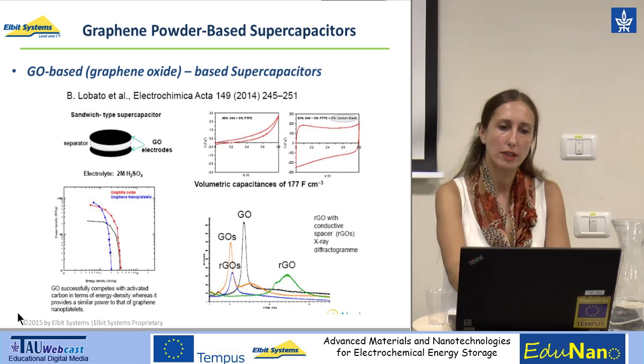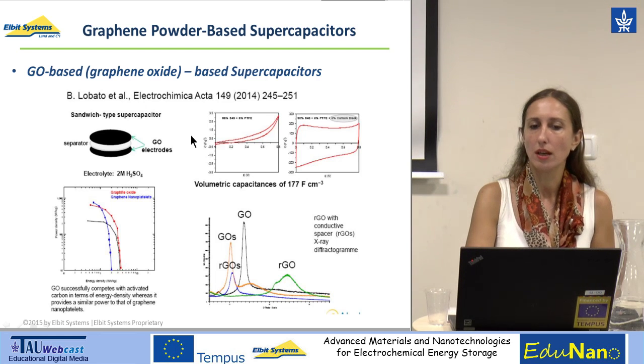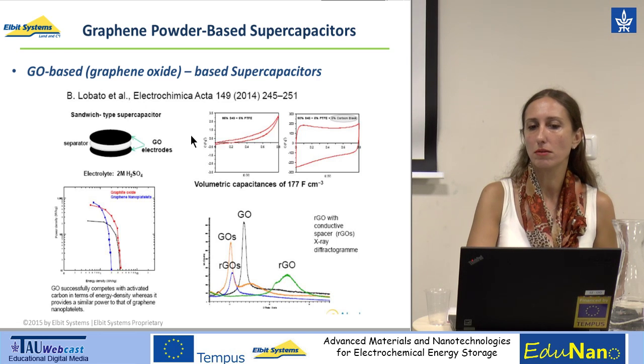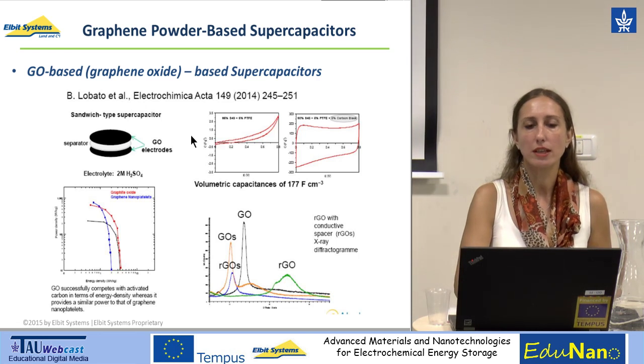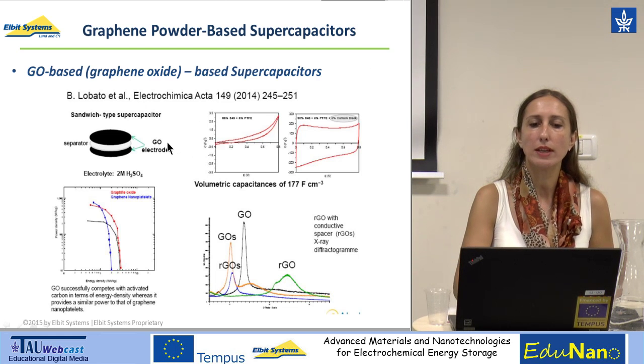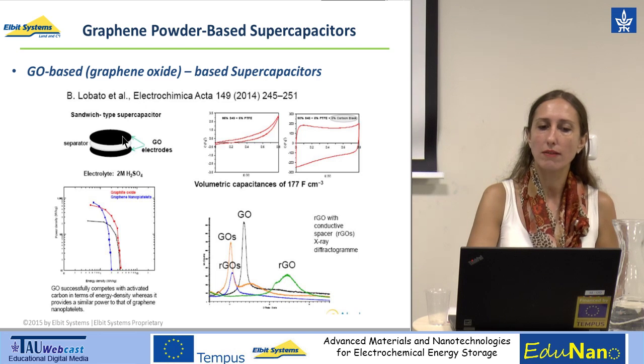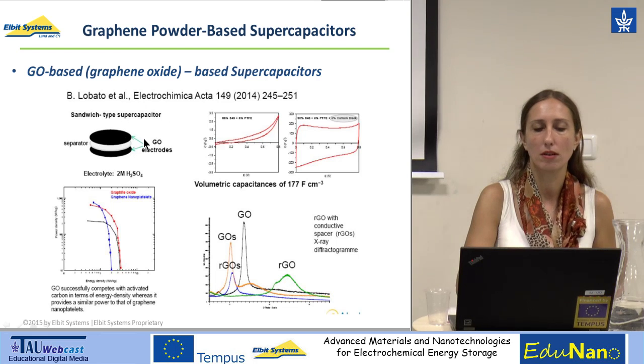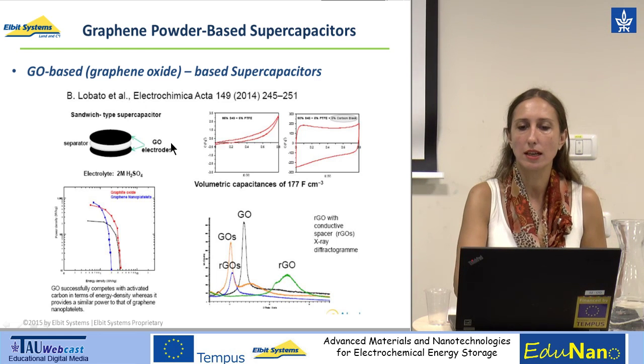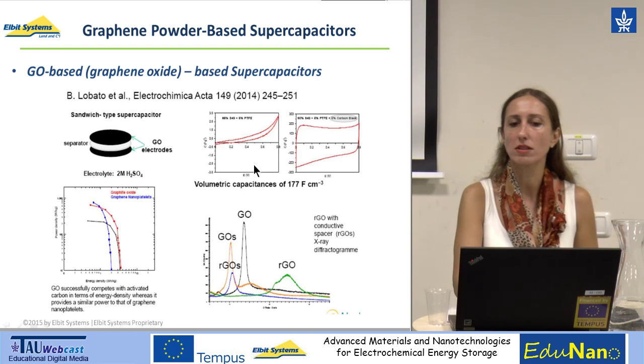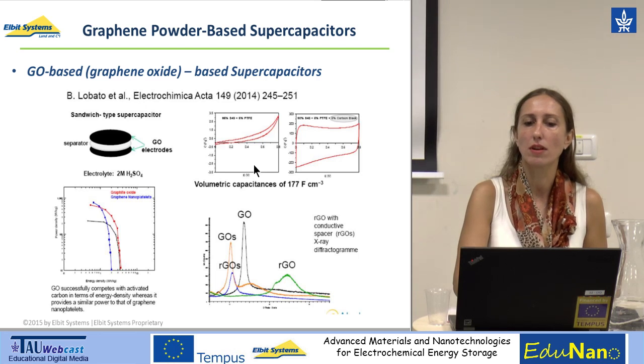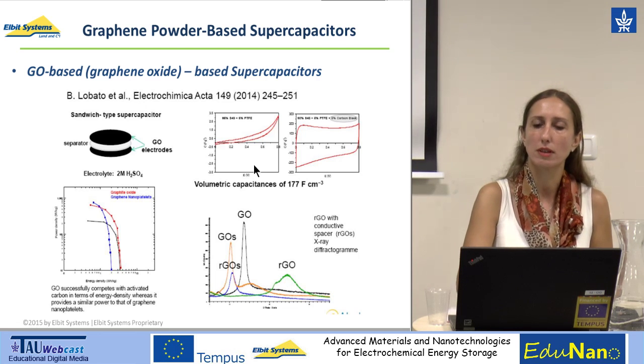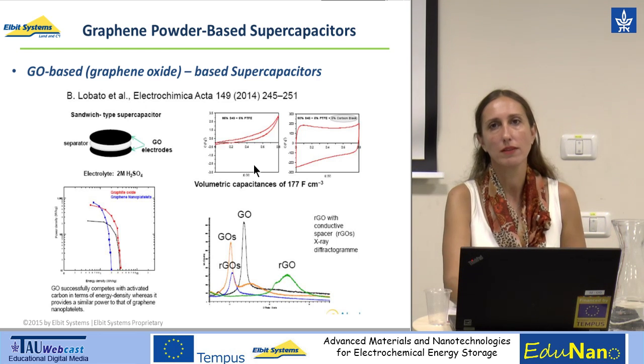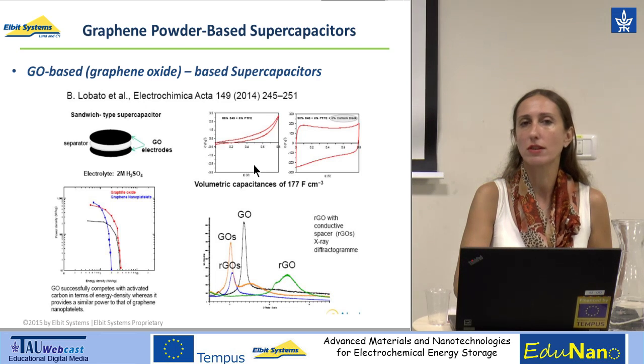For example, what I would like to show here is the research of Lobato et al., published in Electrochimica Acta in 2014, demonstrating a sandwich-type supercapacitor with graphene oxide electrodes. It is actually a coin cell configuration with electrodes consisting of graphene oxide, and the electrolyte is an aqueous acidic electrolyte of 2 molar sulfuric acid. Here we have the capacitance as a function of the voltage. We can see that a volumetric capacitance of 177 farad per cubic centimeter is attained. These are relatively very large values of volumetric capacitance.